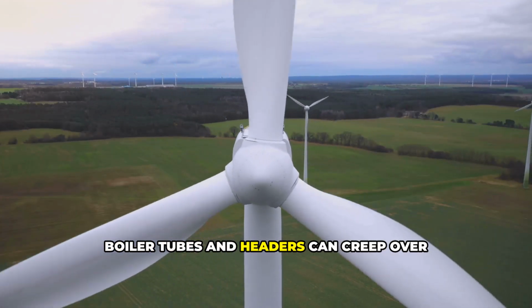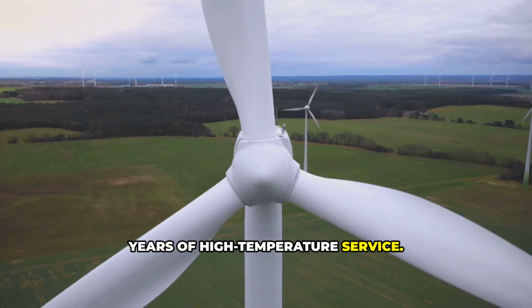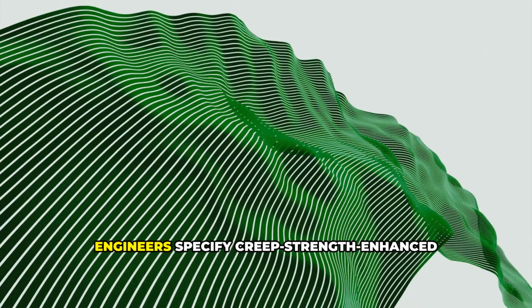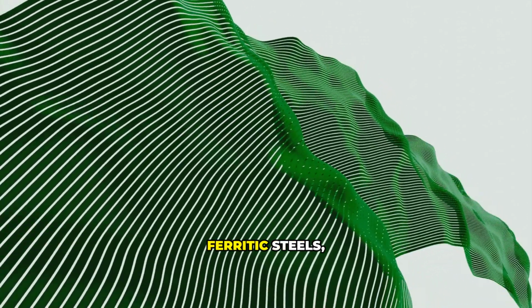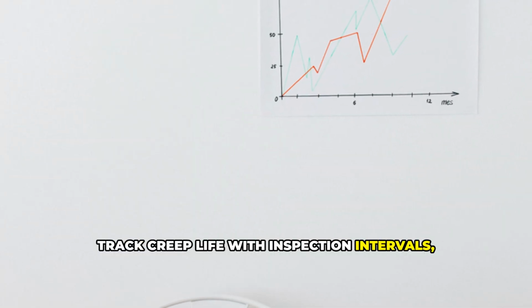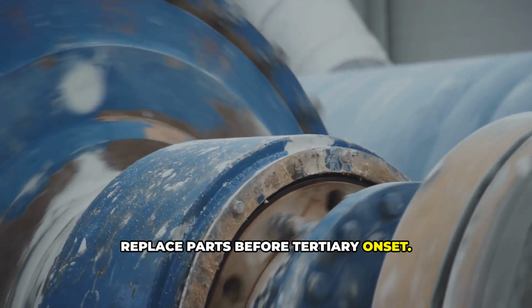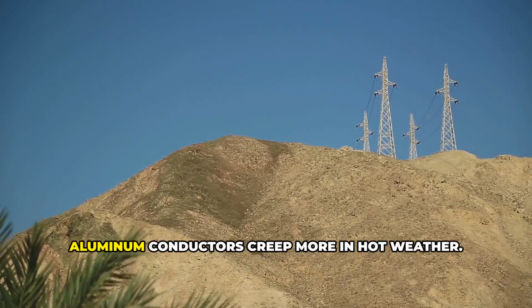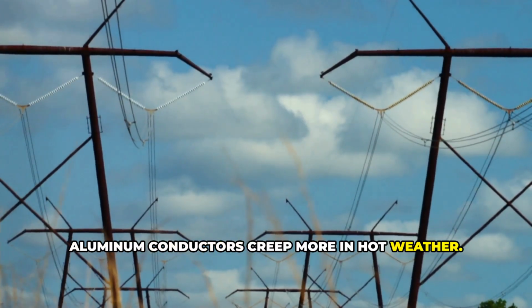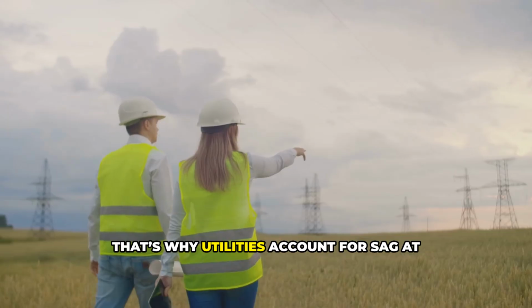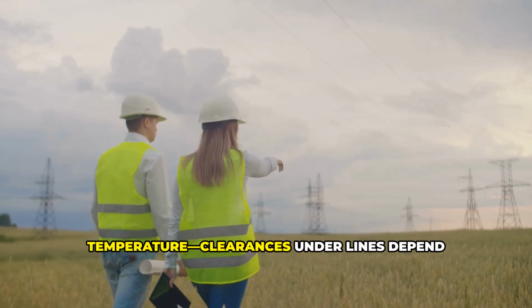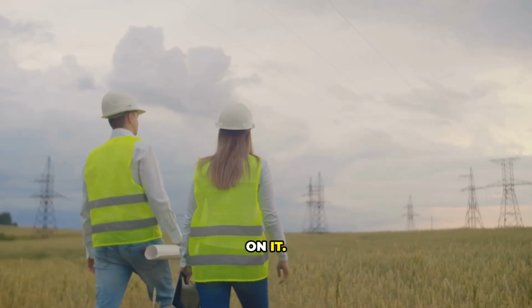Power plants and refineries. Boiler tubes and headers can creep over years of high-temperature service. Engineers specify creep strength-enhanced ferritic steels, track creep life with inspection intervals, and replace parts before tertiary onset. Power lines. Aluminum conductors creep more in hot weather. That's why utilities account for sag at temperature. Clearances under lines depend on it.